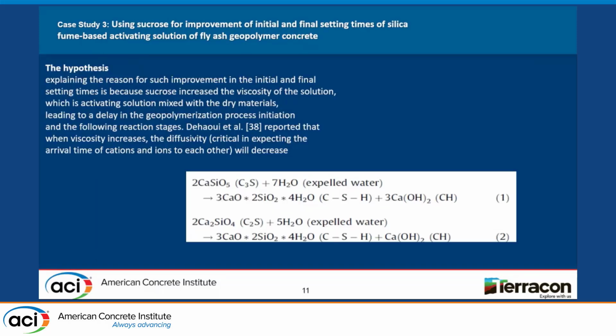So our hypothesis why we are having really good improvement without really needing the external heat, we believe that in the presence of the Portland cement, the expelled water, usually the water that is going to result out of the geopolymerization process, if it hasn't been utilized, is going to evaporate gradually and going to leave micro cracks. So in the presence of the Portland cement, this expelled water is going to be utilized to make CSH, which is good, and also CH, which is calcium hydroxide, which is going to react with the available unreacted fly ash particles.